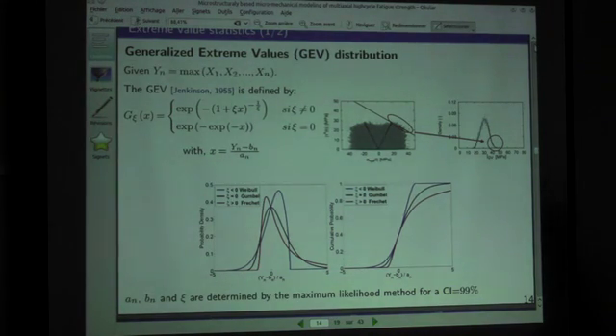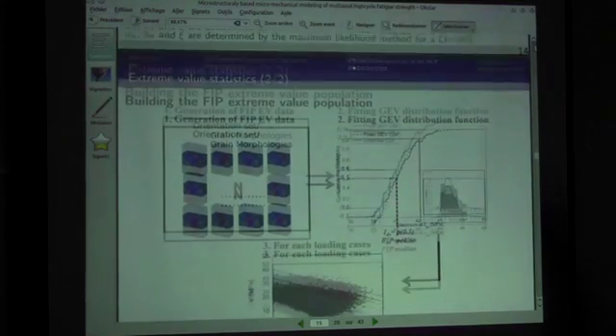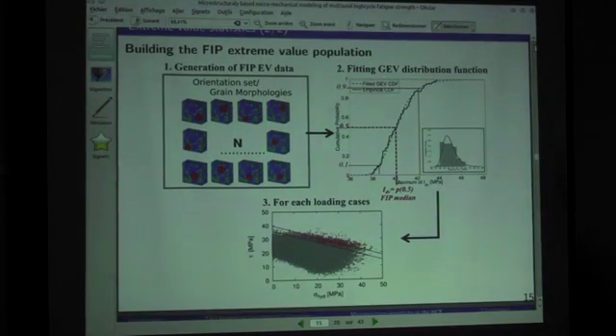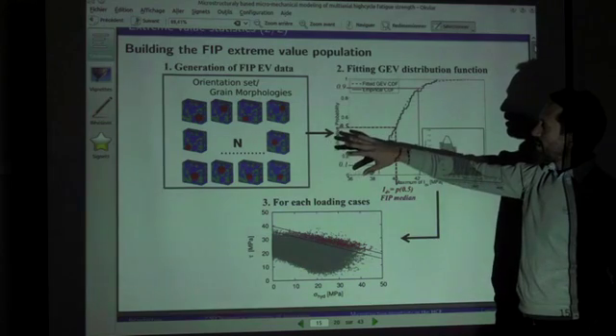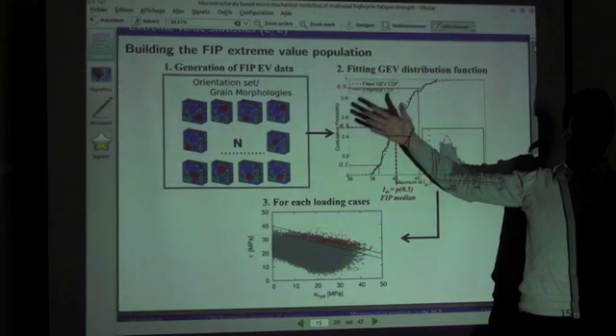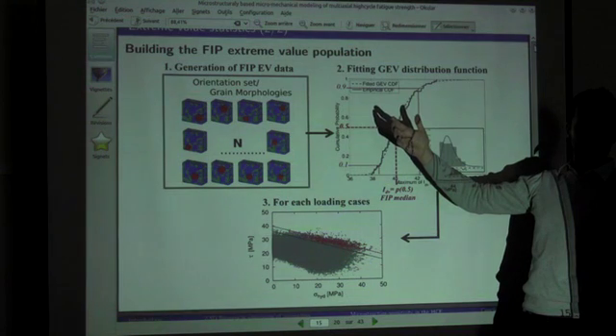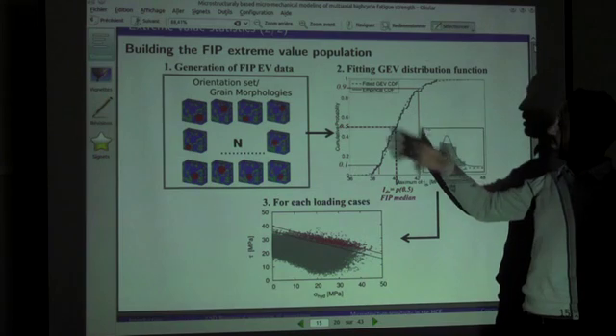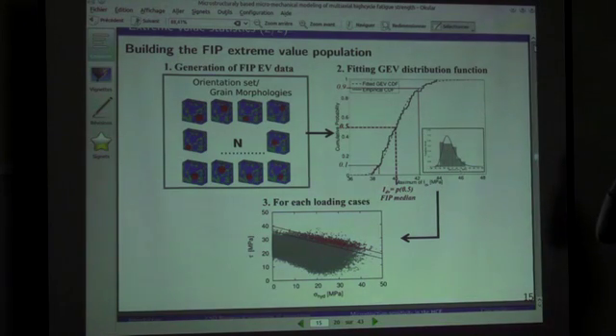So we did this on our aggregates. The main strategy is this one, and it's a similar strategy or analysis that was proposed by David McDowell as well in the same type of computations. So we are doing many computations, many means we're going to 20 to 30 computations of aggregates, 30 aggregates per loading case. And for each aggregate we have more or less 300 grains. It's a few 100,000 elements in each case.